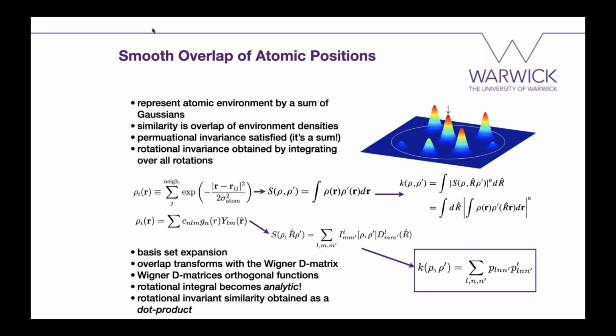So this out of the way, I just want to show what we came up with eventually as a convenient representation. It's called the smooth overlap of atomic positions, where we use a set of Gaussians to represent our atomic neighborhood. So you can see a 2D projection of this. The central atom is in the middle, and all the neighbors are Gaussians around it. And then we also employ a smooth cutoff function to make sure that as neighbors come in and out of the environment, they do it in a smooth fashion.